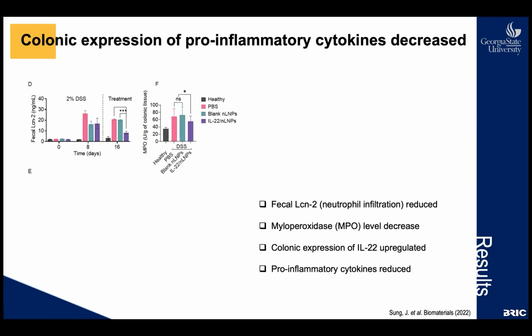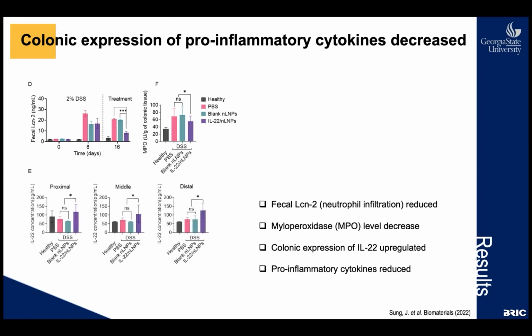Next, we measured the fecal lipocalin-2 level, showing the neutrophil infiltration. The level of lipocalin-2 was significantly increased by day 8 after 7 days of DSS treatment, but after another 7-day treatment of IL-22, lipocalin-2 levels significantly decreased, whereas the PBS and blank lipid nanoparticle groups remained the same or had a little bit of decrease. Also, we measured the IL-22 expression level in the colonic tissues, and we can see here that it significantly increased in all parts of the colon.